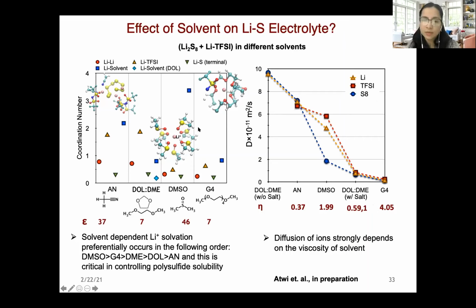That happens because DMSO provides very strong solvation and can dissociate lithium from the anions. And that's why the molecules are moving relatively independently in the solution compared to DOL DME and acetonitrile, where they're moving together in the solution. Okay, and that's why the mobility of ions in this DOL DME mixture is smaller. And for glymes, even though that also acts as a very strong solvent, it also has very, very high viscosity, because of which the mobility of the ionic species is the lowest in this tetraglyme solvent. Okay, so we identified these several different parameters, such as the geometry of the solvent, salt, as well as the viscosity, which is crucial in determining the structural and dynamical properties of lithium electrolytes.